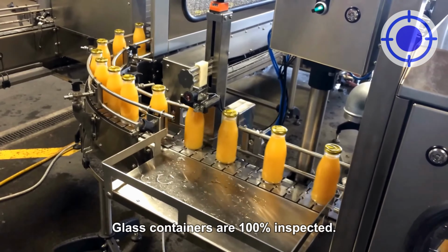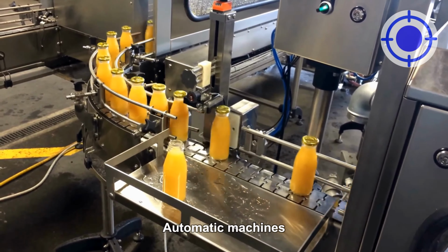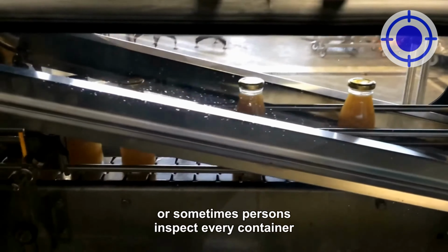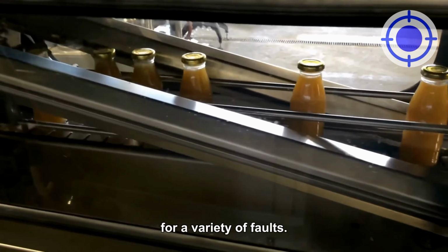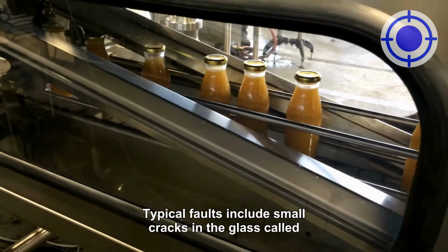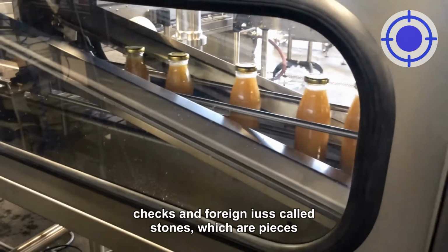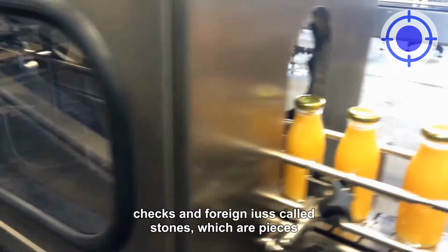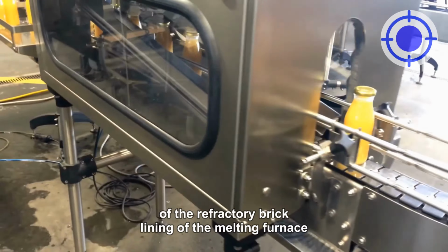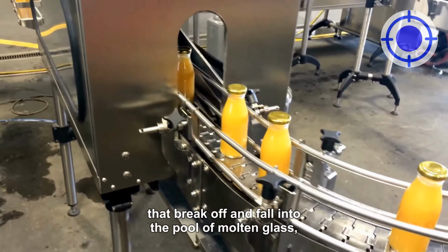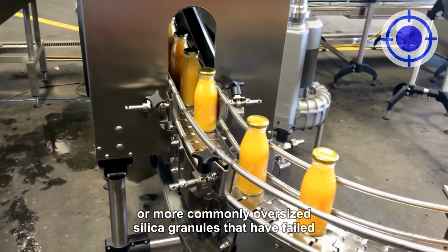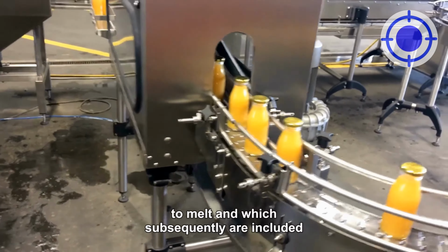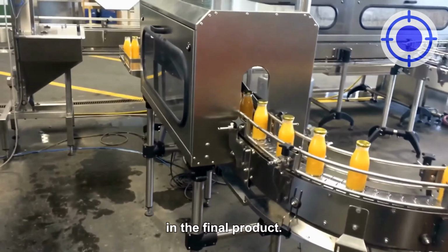Glass containers are 100% inspected. Automatic machines, or sometimes persons, inspect every container for a variety of faults. Typical faults include small cracks in the glass called checks, and foreign inclusions called stones, which are pieces of the refractory brick lining of the melting furnace that break off and fall into the pool of molten glass, or more commonly oversized silica granules that have failed to melt and which subsequently are included in the final product.